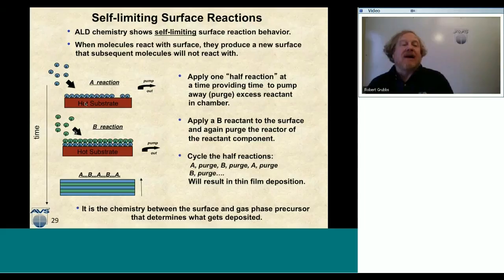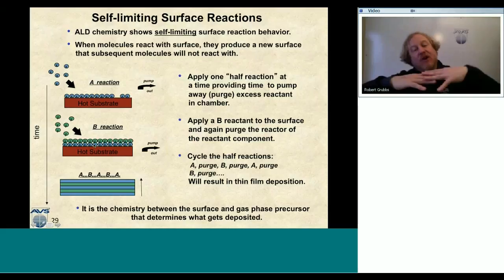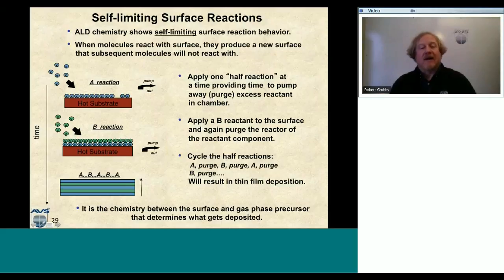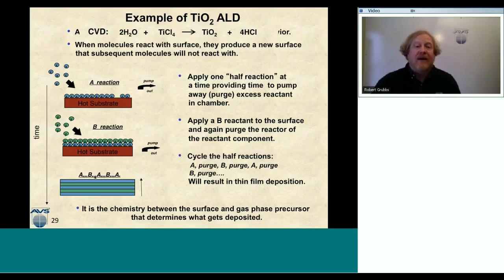Then when they're all pumped out, I can come down with the B reaction. The B reaction comes in and reacts with the A surface, but no more. It doesn't react with anything else on the surface except what the A reaction left behind. And so once that reaction has taken place, no other precursor chemistry will happen, and then I'm allowed to pump that B reaction out. And so as I do the AB sequence, I get this film to grow. So the chemistry between the surface and the gas phase precursors really determines what gets deposited. So these are sort of cartoons, but now let's look into more detail of an actual example of ALD.